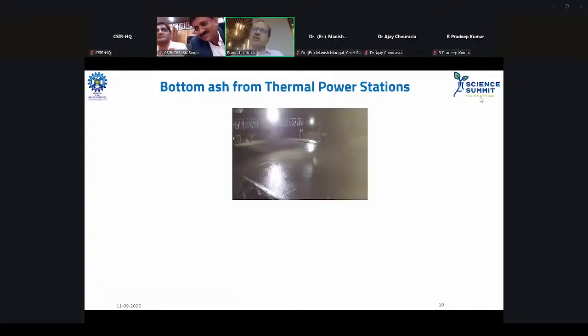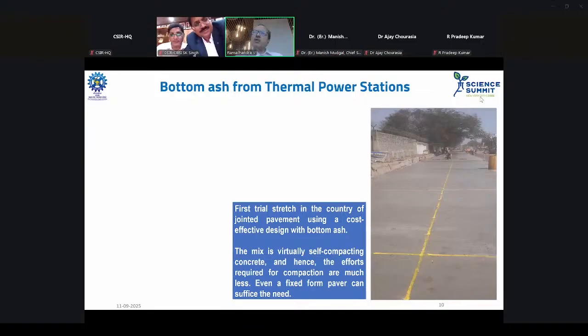Now, this is one example where we were involved in constructing a road with pavement quality concrete in Chandrapur near Nagpur, and self-compacting concrete was made by using 50% of sand replaced with bottom ash. Of course, there is a slight difference in the properties of fine aggregate, natural sand and the bottom ash. By designing it properly, we were able to make an excellent concrete road which is performing quite well.